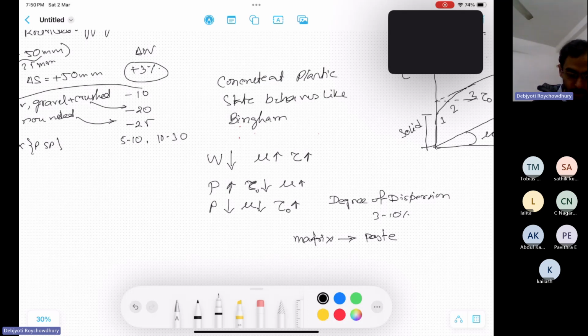So normal strength concrete has a water cement ratio more than the normal consistency, at 26% to 33%. The paste content shall be adequate not only to fill the voids in the aggregate but also more than that, for proper dispersion. So the paste content should be adequate to fill the voids, and care should be taken that it does not disperse the aggregate. For economy and other factors, the paste content in normal concrete ranges from 28 to 32%.